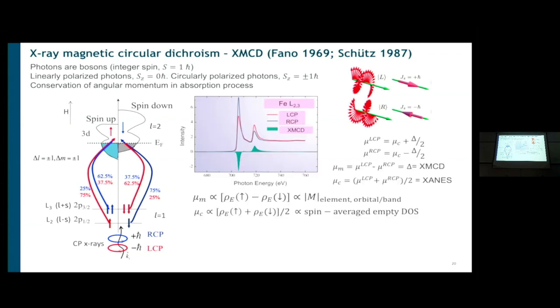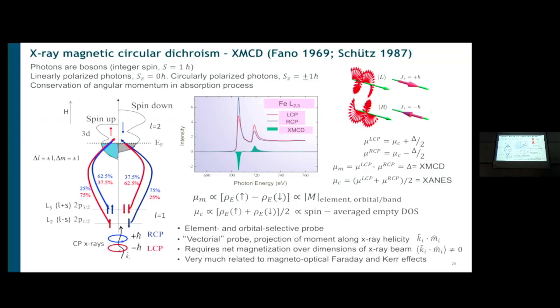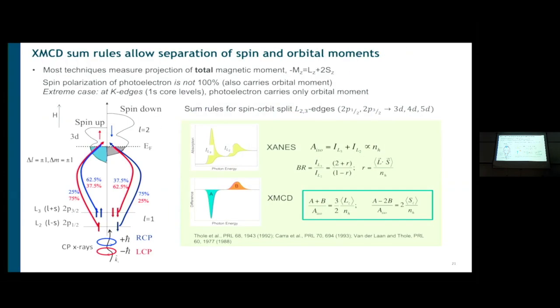So the measurement is very simple. You measure the absorption for one helicity, the other, and you can take the difference to remove the magnetic part from just the simple X-ray absorption, which is the charge part, and the spin average empty density of states. And this is, again, element and orbital specific, and it's a vectorial probe because it measures the projection of the magnetization, which is the quantization axis, along the X-ray helicity. So if you magnetize the sample perpendicular to the X-ray helicity, you see nothing. So you have to magnetize the sample with a projection of the moment along the X-ray helicity. And this is very related to magneto-optical Faraday and Kerr effects. Basically, it's the X-ray version of those magneto-optical effects.